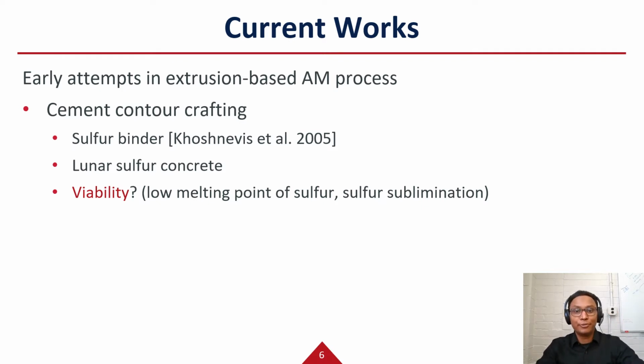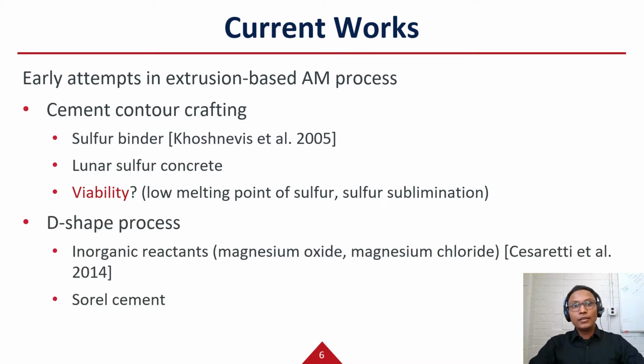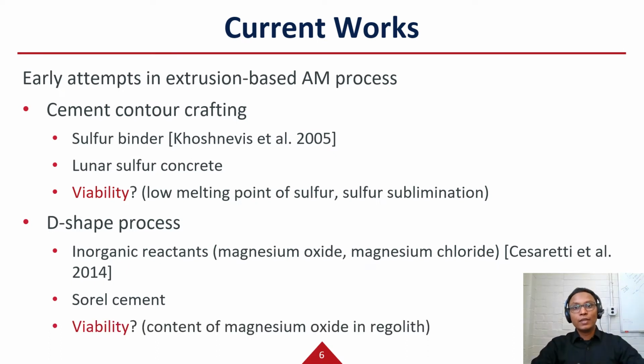Moreover, we have the additional prerequisite of mining sulfur in the moon, as well as potential sulfur sublimation in the vacuum environment. On the other hand, Cesaretti adapted the D-shape process to 3D print lunar regolith. They utilized two inorganic reactants, magnesium oxide powder present in the lunar regolith and a binder consisting of magnesium chloride. These two reactants undergo a chemical reaction to produce the Sorel cement. However, this process relies on the chemistry of the material. The material composition of the regolith can vary depending on the landing location on the moon. Besides, the magnesium oxide content might not be sufficient for the binding reaction.